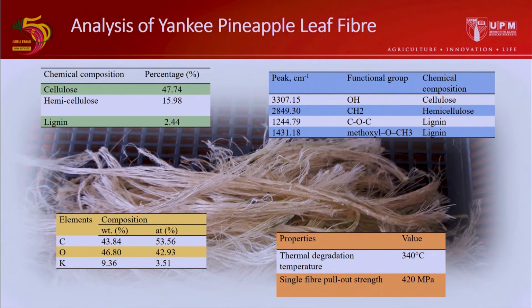The result shows the presence of carbon, oxygen, and potassium in the fiber. The carbon contained 43.84% in weight and 53.56% in atomic. The oxygen contained 46.8% in weight and 42.93% in atomic, and potassium 9.36% in weight and 3.51% in atomic.